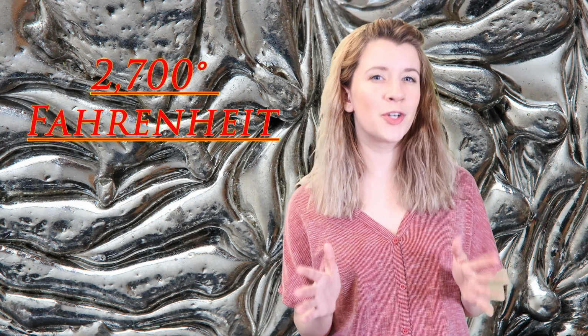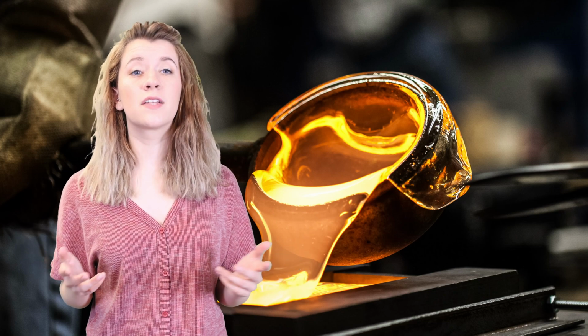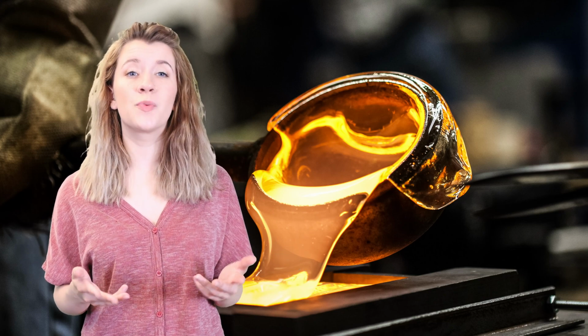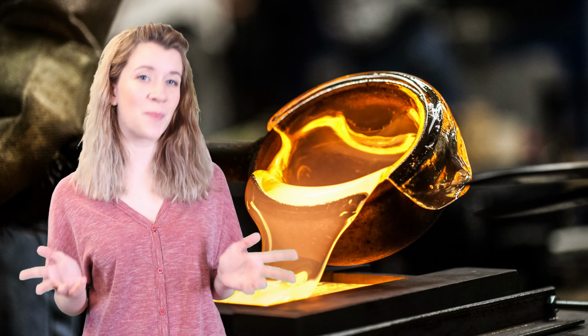The term annealed is generally referring to the cooling process of the glass. Once limestone, soda ash, and several other things are melted at 2,700 degrees Fahrenheit, the liquid mixture is floated on a pool of molten tin. This is where the term float glass comes from. After this process, the glass is slowly cooled and stretched, which helps reduce internal stress that could cause breakage. When glass is annealed properly, it's less prone to shattering or breaking.